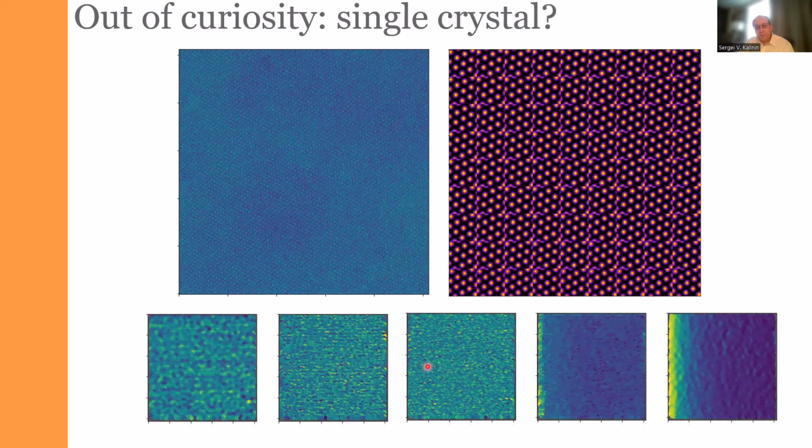They're absolutely random. But what's interesting, if we look at the latent 1 and latent 2, you can see a very clear contrast from the left to the right, which is pretty much invisible in any other way. So where does it come from? Electron microscopes have a flyback delay, which is a non-ideality of the scanning.